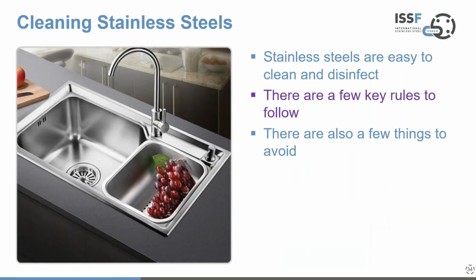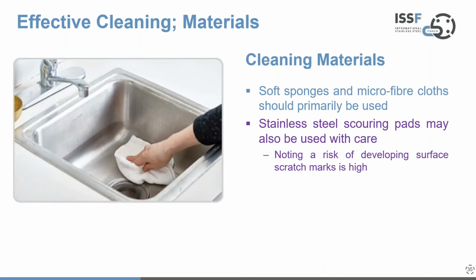Now, as we get towards the end of this webinar, I'd like to move on to look at two further aspects. One is cleaning stainless steels, and stainless steels are easy to clean and disinfect. There are a few key rules that we need to know about, and there are a few things to avoid. So we'll start with cleaning materials. Generally, you should clean stainless steels with soft sponges and microfiber cloths. That's the primary choice. It is possible to use stainless steel scouring pads, but with care, because you have a high risk of developing surface scratch marks. But used with care, they'll be effective.